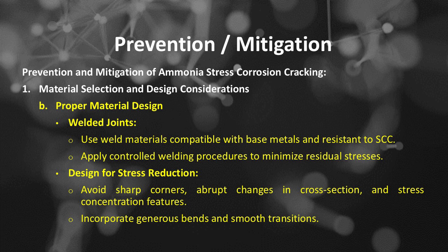Number B is proper material design, which includes: the first is welded joints, use weld materials compatible with base metals and resistant to SCC, and apply controlled welding procedures to minimize residual stresses. The second is design for stress reduction, avoid sharp corners, abrupt changes in cross-section, and stress concentration features. Incorporate generous bends and smooth transitions.